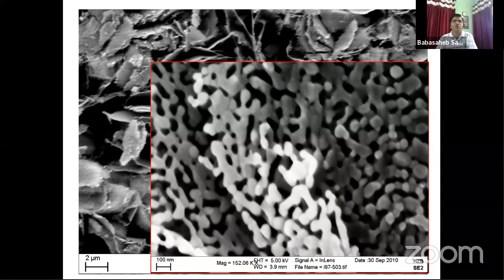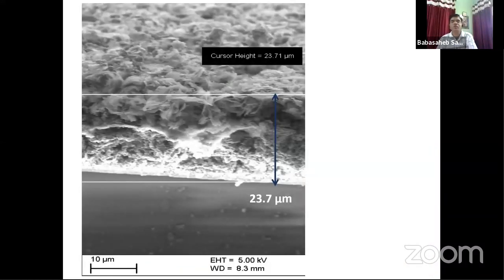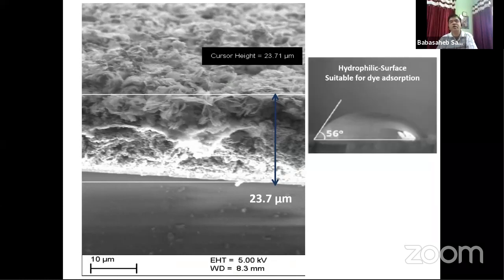So this is a cross-sectional image of the zinc oxide, where you can see its thickness. We also tested with the wettability test whether the zinc oxide is hydrophilic or hydrophobic, and we observed a 56-degree angle, which is hydrophilic in nature. So there is a possibility for the dye to adsorb on the zinc oxide from aqueous as well as non-aqueous solution.